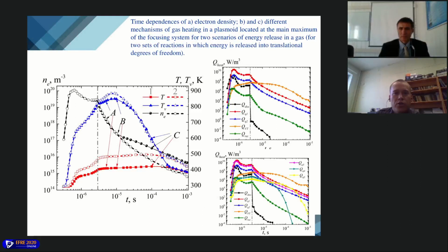The release of energy in the dissociation reaction is then the subsequent part of the active phase. The dominant mechanism is a self-exciting reaction, which dominates up to 6 microseconds. And next we can see that the vibrational-translational mechanism is dominant.